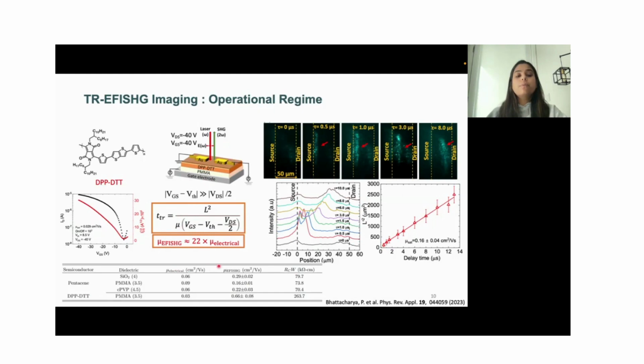And it has been found from our studies that the carrier mobility found from EFISH measurements was almost 22 times higher compared to what was measured using IV characterization. The table at the bottom of the slide shows a few other examples of semiconductor FETs where the effect of the dielectric constant as well as the high contact resistance can be seen directly translated into the underestimation of the electrical carrier mobilities, where the EFISH carrier mobilities then give us more intrinsic values.